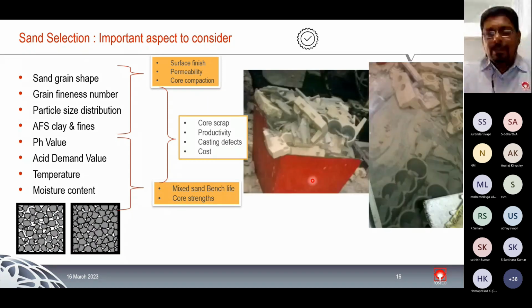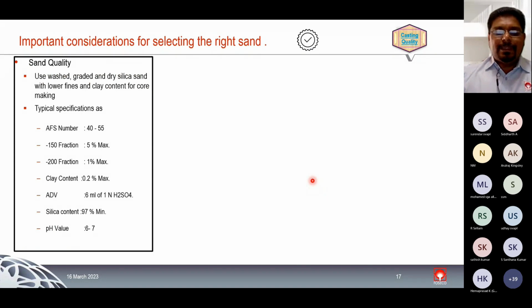The core is not getting burned, and the core sand is getting diluted into the green sand mold, which will accumulate nitrogen in the green sand. This is very important. If the combined influence from the melt, the core, and the green sand molding on the quality of the casting exceeds the threshold limit, then it will result in a nitrogen fissure.